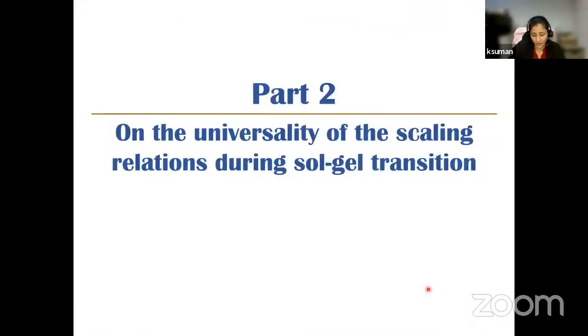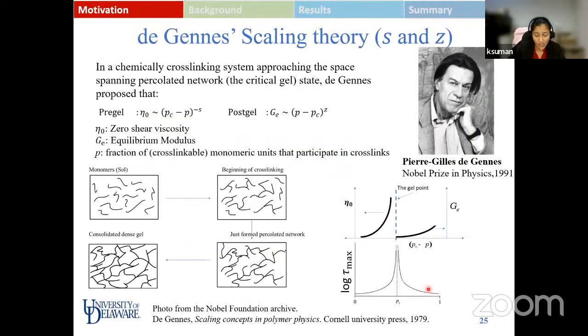And with this, we move to the second part of the talk, which is on the universality of the scaling relations during the sol-gel transition. So we are in the community of soft matter, and we all know Pierre-Gilles de Gennes, and he had proposed that for a chemically cross-linking system, while approaching the critical gel transition, properties like zero shear viscosity and equilibrium modulus diverge in the vicinity of the critical gel point.